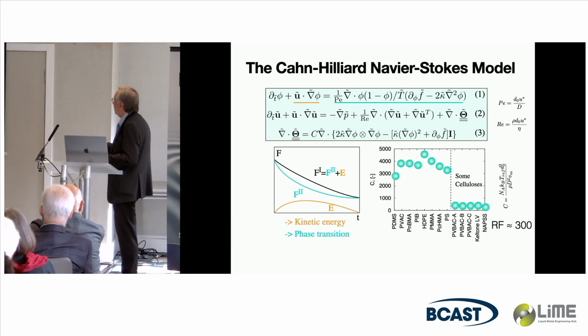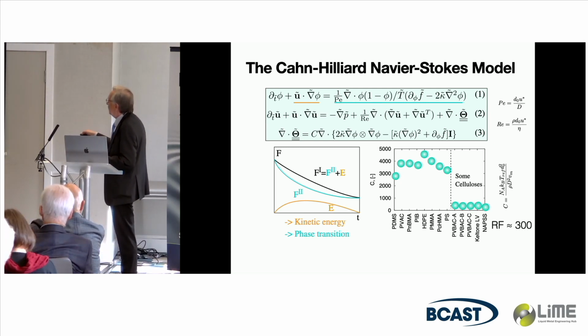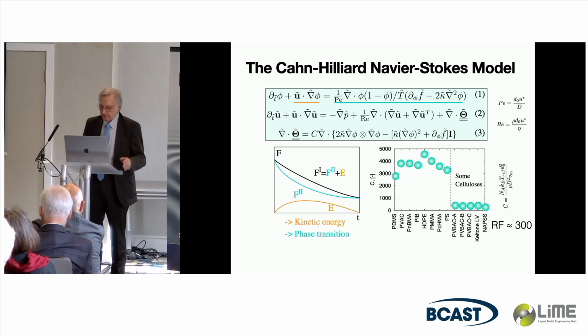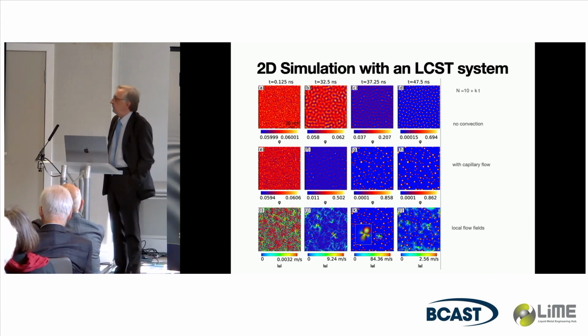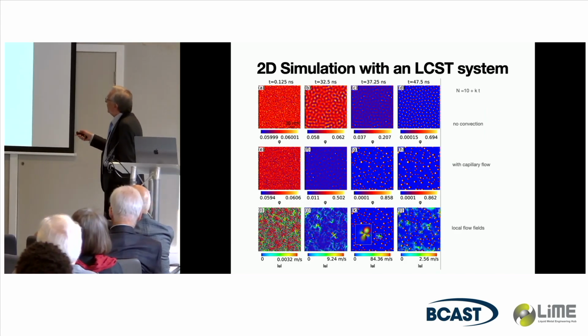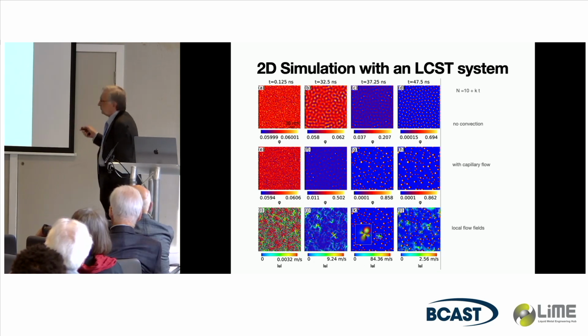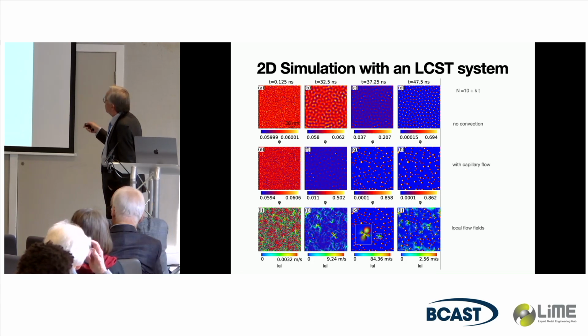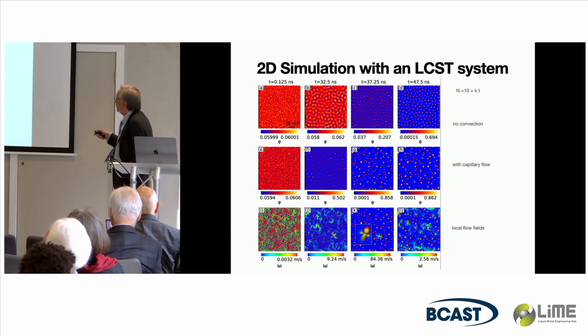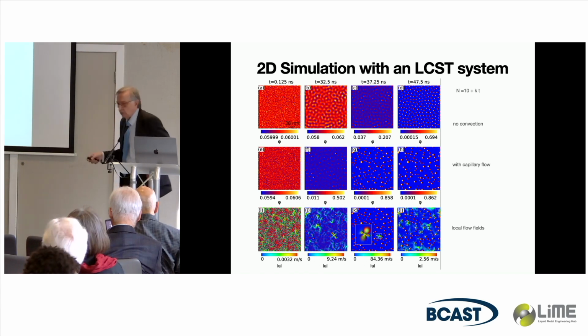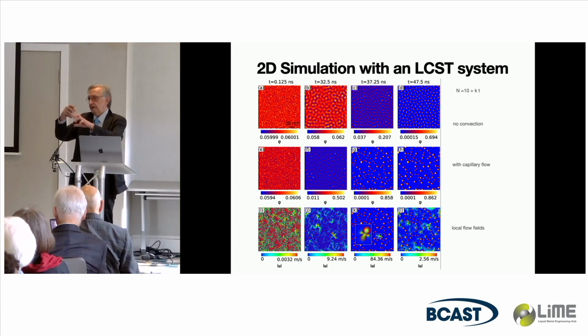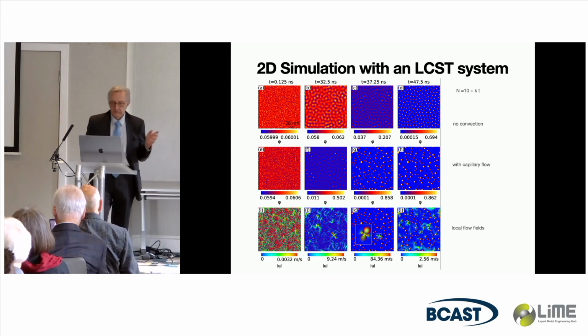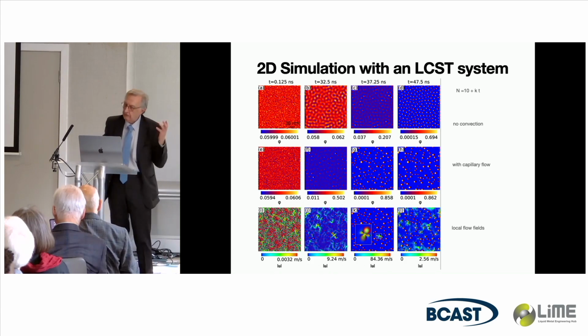to describe interfacial-driven convection. And we calculated this capillary number here for a resorcinol formulation. It's around 300, so there will be an effect. First, what you do is, of course, 2D simulations, and then start with 10, so just inside the spinodal, and you see from concentration fluctuation that particle droplets appear. And if you have capillary flow, instead of being regularly arranged, they are irregularly arranged, looks similar to monotectic alloys. And this is just to show that the droplets coming closer have interaction of the fluid phase fields, the solute fields. This is well known since 1959 or something like that.